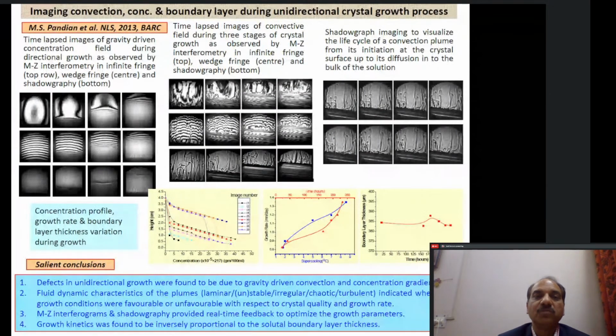In these imaging experiments which we performed, we were able for the first time to show that it is the gravity driven concentration gradient which is set up inside the crystallizer, inside those ampules, which is actually allowing us to grow the crystal. And this work has been published in a very good journal, and it has been received very well by the international experts. So we were the first to show that in SR growth how a crystal is growing using convection and gravity-driven convection gradients, and also the concentration gradients.